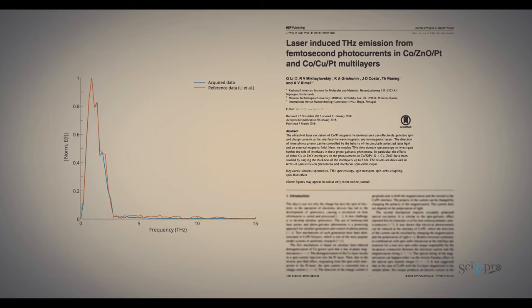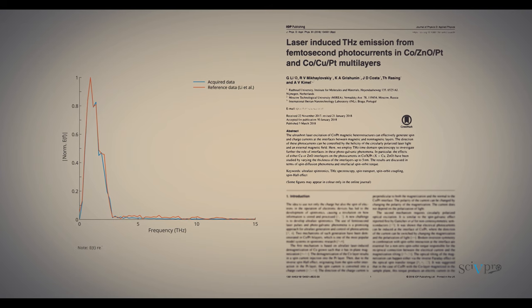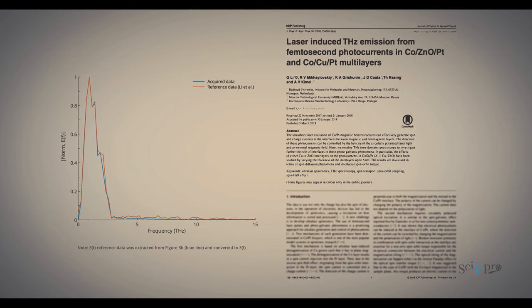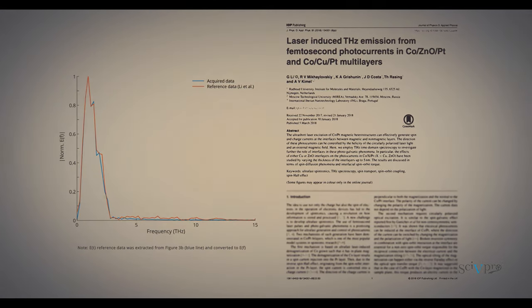This is a comparison between the FFT of the acquired data and the reference FFT from the terahertz signal emitted by cobalt-platinum as reported in the literature. The good match between measurements suggests that the setup is well configured and ready for an actual measurement.